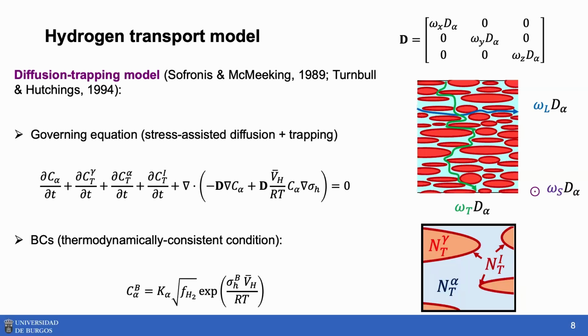Our idea was to combine both classical frameworks: the framework from Sofronis and McMeeking, where you can capture the influence of hydrostatic stress and also of trapping, and the modifications that Turnbull and Hutchings made to account for the particularities of a dual microstructure with a very low diffusivity, the austenite, and a very high diffusivity, the ferrite.